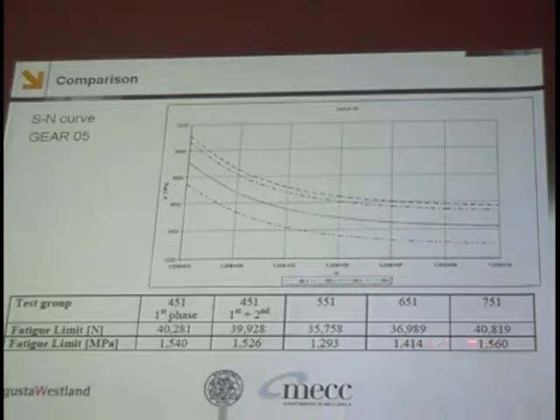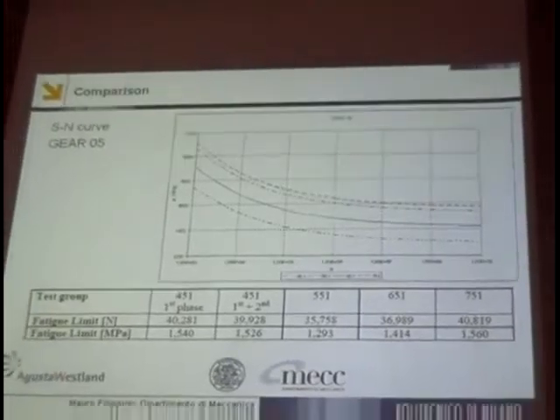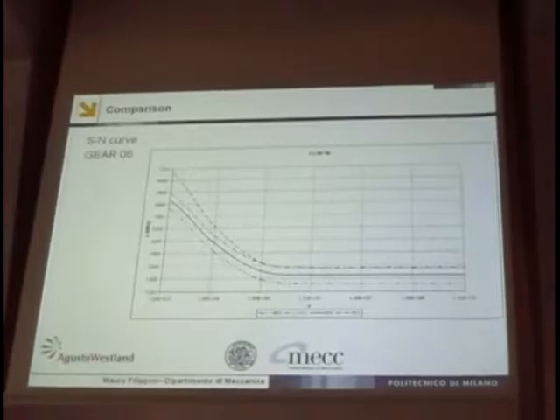And here you will see also the fatigue limit in terms of stress for the other conditions. It's rather high for conventional materials, but this is due to the presence of high residual stresses and the high gradient that we have in the tooth.